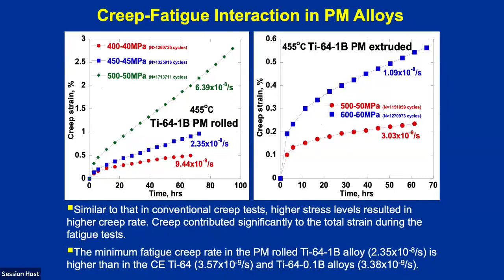We basically know that there's some ratcheting going on in the material. And if we look at this, this is a PM extruded, we know that it's going to ratchet just like creep and be a function of creep at the certain conditions. We can measure this ratcheting rate and apply it for both of these conditions and try to mimic and model what's going on in terms of the fatigue, in terms of the creep behavior, to understand why we're not getting the best performance in the PM extruded material.